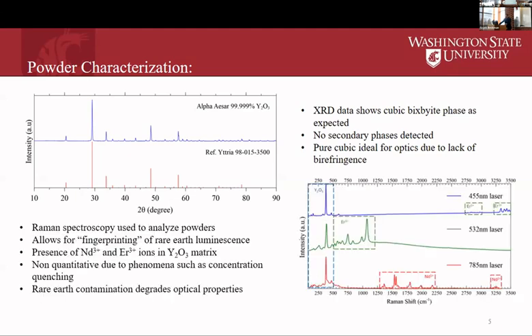What we found was we had pure cubic Bixbyite phase, no secondary phases, although just because it was pure cubic Bixbyite doesn't mean there aren't other contaminants. So we did Raman spectroscopy on it, and found the presence of primarily neodymium oxide and erbium oxide, which we were able to see with the rare earth luminescence. It's important to note that this luminescence isn't really a quantitative measure—generally speaking, we can't tell how much of it we have, we just know that we have some of it.